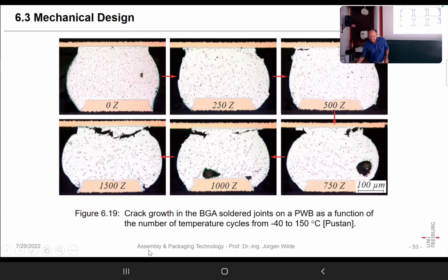Okay, but we also see on the underside, also here, cracking already starts. What is also interesting is to know the material itself also changes. Yes, between 500 and 750, we see the structure becomes much more coarse compared to the initial structure. If you have engineered parts from mechanics, they will never change their internal structure. They stay as they are, but solder joints don't.